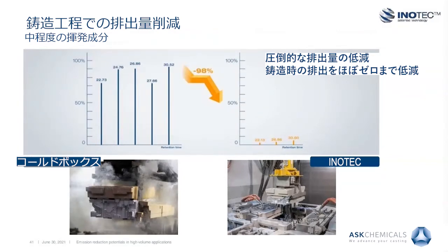The picture on the right shows the exact same casting process with a slight but very important difference: that the INOTEC technology is used. In comparison, the formation of pyrolysis products from the binder system is completely absent. The INOTEC binder system is only dehydrated and converted to a glassy state by thermal strain of the casting process and remains inside the sand cores. A gas chromatographic analysis of the emission stream shows that 98% of the emissions can be reduced. The main improvement here results from the absence of medium volatile compounds, which are responsible for BTX emissions in the casting process using polyurethane standard cold box binders.